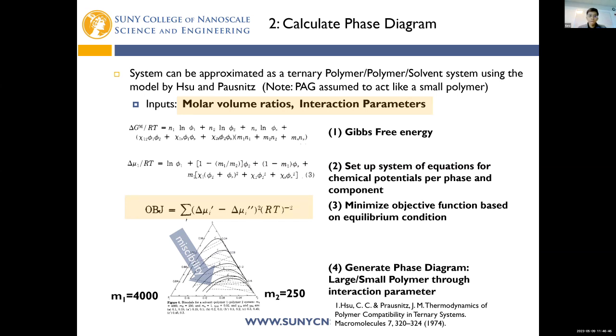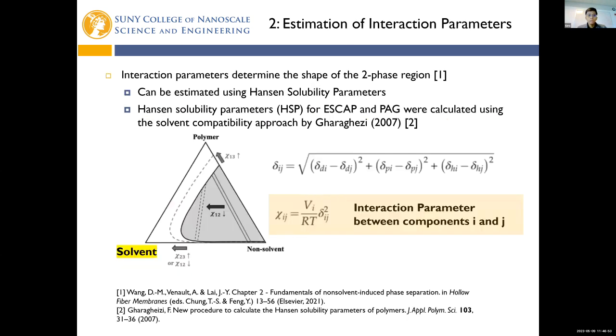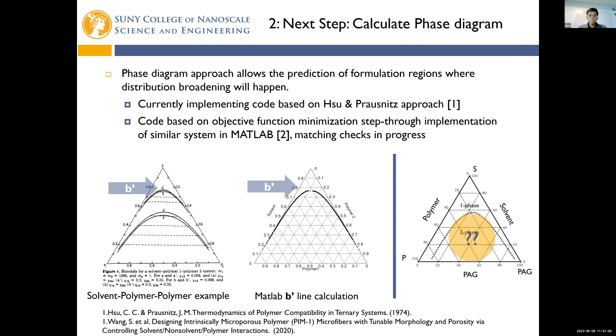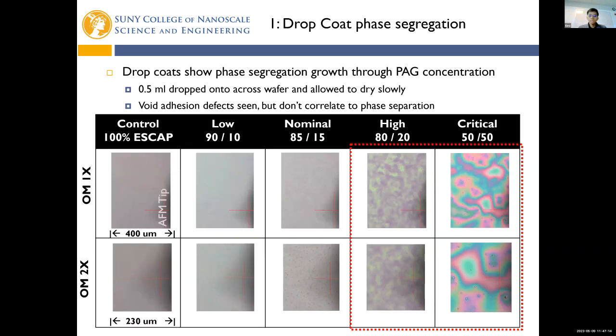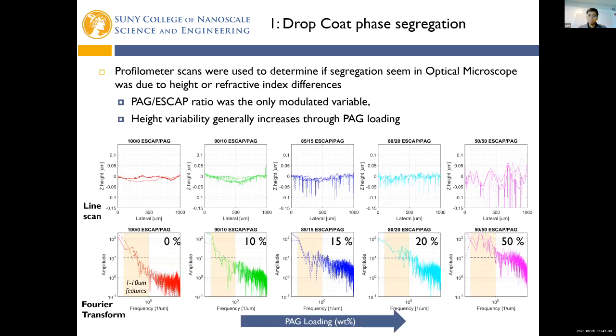standard thermodynamic phase diagram calculations based on Gibbs free energy of mixing, as well as interaction parameters. And then I used those interaction parameters to define our particular system, for which I wrote some initial MATLAB code to try to understand where this exists. So there was some preliminary work, as well as some experimental work to show that we do see phase segregation in these systems at our expected concentrations, and we can see physical differences in them.